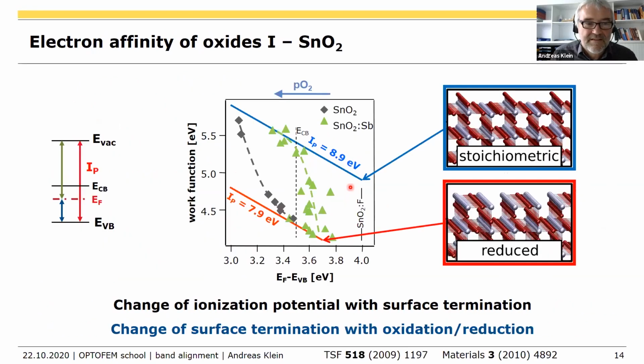Okay. If it comes to oxides, there is a difficulty because we are using the electron affinity. And if you have an oxide, the electron affinity is not a unique quantity. Very simple, this is the first example. That's tin dioxide. So these are work functions measured as a function of the Fermi energy from UPS measurements, photoelectron spectroscopy. That's nice because you get two quantities. You get this quantity and you get this quantity. Both come out from the experimental measurement.